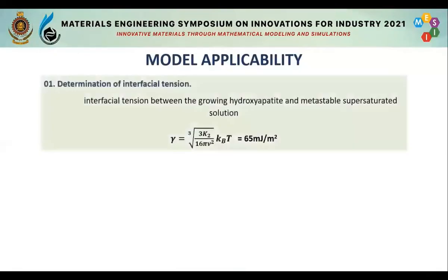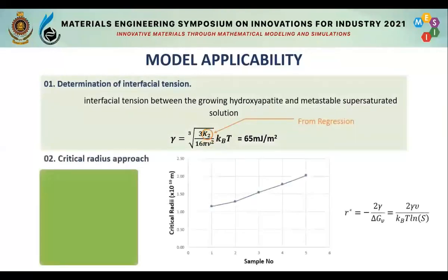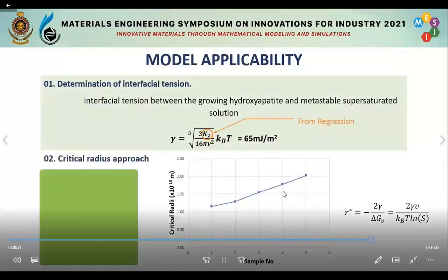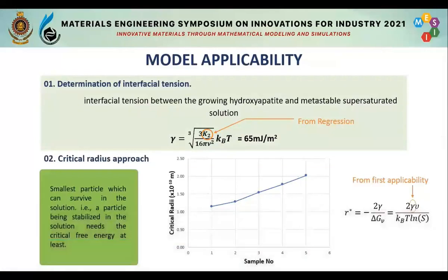into the crystal structure. We applied this model to some nucleation aspects, basically to determine the interfacial tension with the determined kinetic constant. Then, based on that kinetic constant, we calculated the critical radius for all samples. Sample number 1 has the lowest critical radius, and sample number 5 has the highest critical radius. So critical radius is the smallest particle size which can survive in the solution.